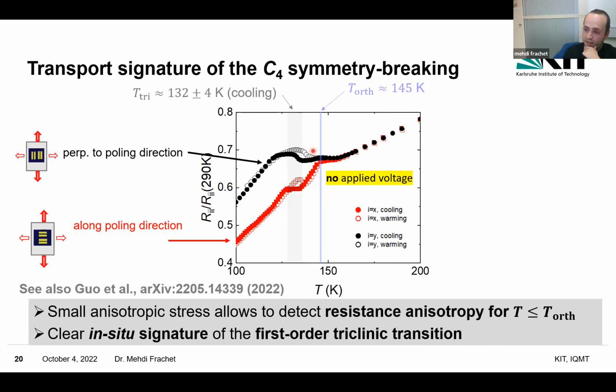So in the tetragonal state, the resistance anisotropy that you can observe should be only due to the strain that you apply. But within the orthorhombic state, it could be different. If you apply a small strain or a small stress, you can have a large resistance anisotropy, which gives you a far too large elastoresistance coefficient that you don't have experimentally. So we should be able to compare, but only when the system is in the tetragonal state.